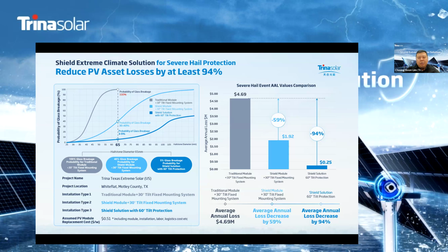So when we translate this into actual financial numbers, if you're going to have 100% breakage, the replacement cost of the PV assets is going to suffer a great loss in monetary terms. But by using the Trina Shield solution, you can see that we can greatly reduce the possible loss from the hailstone attack, by 59% for solution 2, and by up to 94% for type 3.